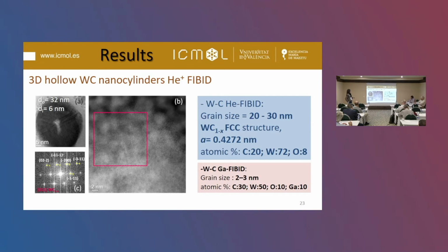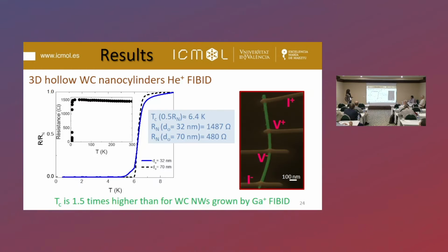Regarding the composition and microstructure of this material, we obtained that the grain size is around 20 to 30 nanometers, and the crystallographic structure is compatible with the tungsten carbide FCC structure. The atomic percentage of tungsten was around 72%. If you have a look at this small box, those values are really good and better regarding the crystallinity and the higher tungsten content compared with tungsten carbon wires grown using the Ga+ FIB.